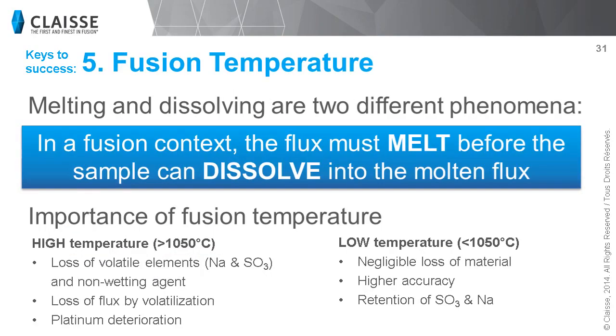It is very important to understand that melting and dissolving are two different phenomena. In fusion, you must melt the flux in order to dissolve the sample into it. So the temperature of the fusion process has to be high enough to melt the flux but not the sample. Usually, a temperature around 1000 degrees Celsius is enough. Repeatability is also a key to success for any analytical method. More important than the temperature used for your fusion, your apparatus shall give you precise and repeatable temperature control fusion after fusion. You also have to keep in mind the analytes when you are selecting your fusion temperature. High temperature may make you lose more volatile elements and it will quickly deteriorate your platinum ware.